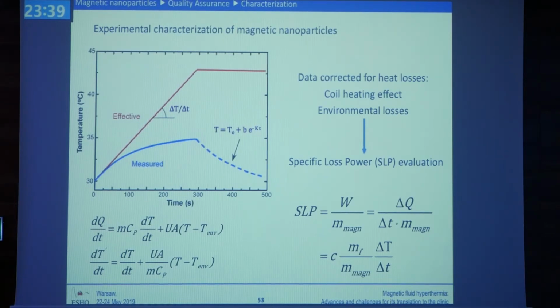When you have heating of your sample with the nanoparticles, you usually also have a heat exchange with the environment. So this means that after some time, what you measure will not be the temperature rise in an adiabatic system. This is not a closed system, it's not an adiabatic one. You have heat exchange. So what we do is we switch off and we measure what heat exchange there is when we switch off, and that we subtract from the measurement and we calculate what would be the actual adiabatic heating of the sample. And from that, of course, we can calculate the specific loss power, which is the heating efficiency of the nanoparticle. This is how many watts per gram of ferromagnetic material are created inside our volume.